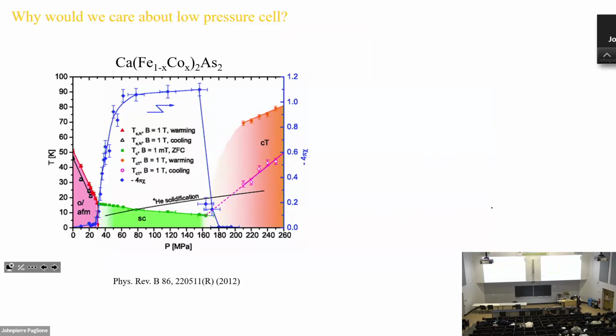One, some materials are really sensitive to even slight pressure. This is, at the time I made the crystals, so someone else did the high pressure study. This is an iron-based superconductor. And the idea behind this is superconductivity is in the close vicinity of the magnetism. And here we have a cobalt dope. And if you don't apply pressure, it's anti-ferromagnetic state. If you apply slight pressure, you can drive this down to almost 0 and go into a superconductor state, then go into a non-magnetic so-called collapsed tetragonal phase.